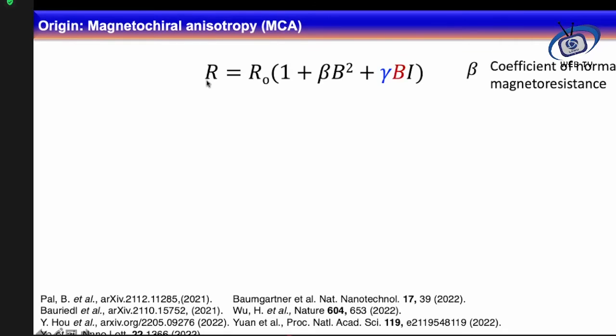Here we can try with a very simple equation. This is the resistance equation, and this resistance is a function of the applied magnetic field, so you can call it the magnetoresistance. And this magnetoresistance has three terms. The first one is just the residual resistance, which is independent of the magnetic field. It does not change by the applied magnetic field. The second term has a beta, and this beta is the normal magnetoresistance coefficient, which depends on B squared. So when you apply the magnetic field, of course, the resistance of the system would change, and this is the normal behavior. But the last term here has three parameters: gamma, B, and I.